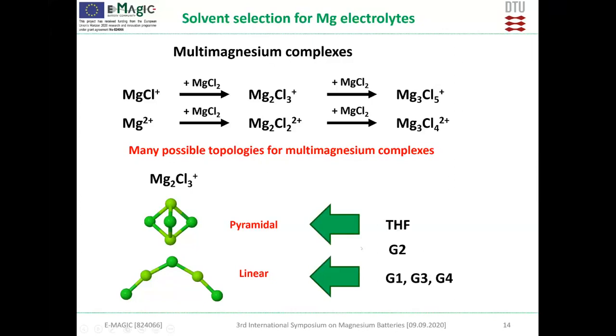If you look at the glymes, they have more chelating characteristics. So they want to make some kind of disk around magnesium, and that limits access to the magnesium from chlorine, and that's why they prefer a linear one. But what's interesting here, if you look, is that diglyme is behaving quite differently. It's also creating linear structures, but they are more condensed and going more in the direction of being more aggregated. So we can do that for all of the clusters.